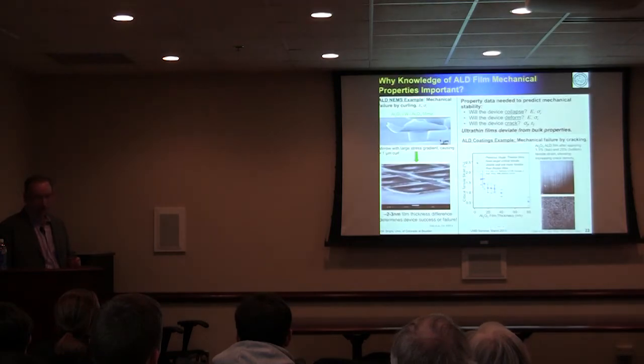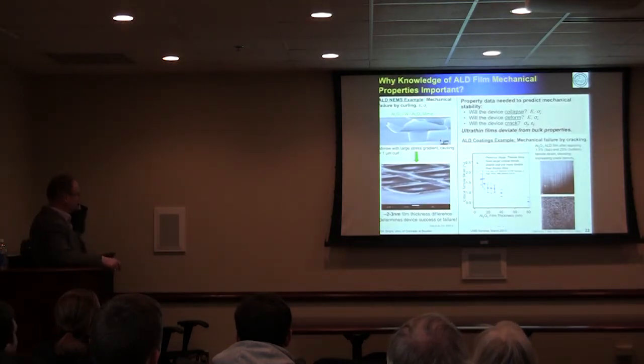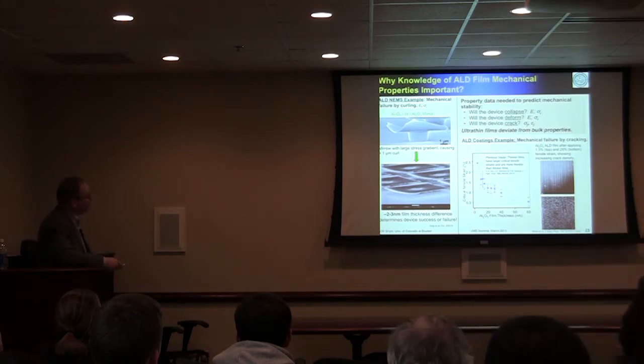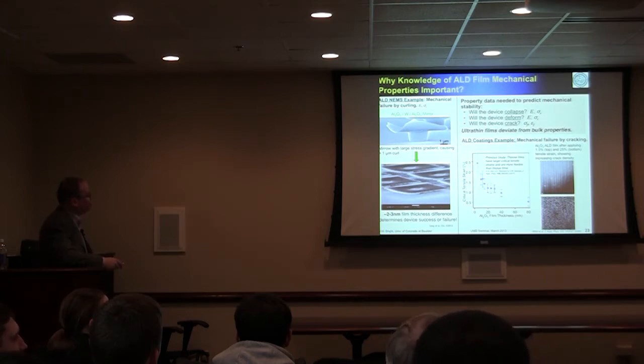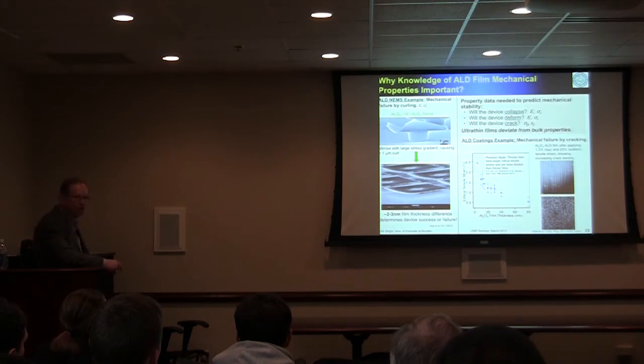So here is an example of where the mechanical properties matter. Maybe start actually in this corner right here. Here is an example of critical tensile strain versus aluminum oxide film thickness. And you can see that the thinner the film gets, the higher the critical strain, which is something you would expect. But still, how to model that at this nanoscale, we don't know. There are some ideas on that, some models we could apply, but this is not a well understood problem.